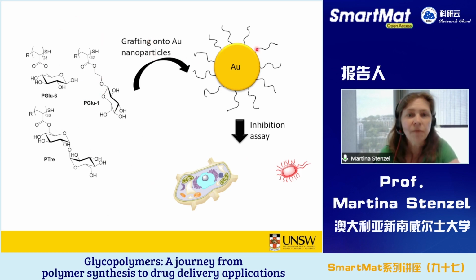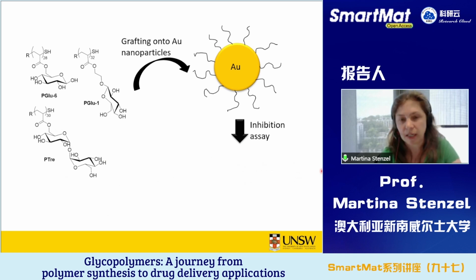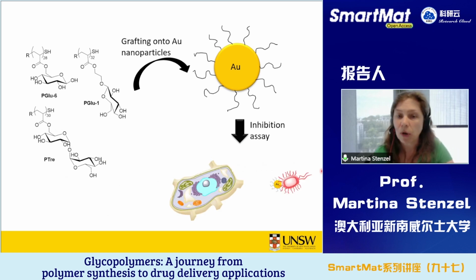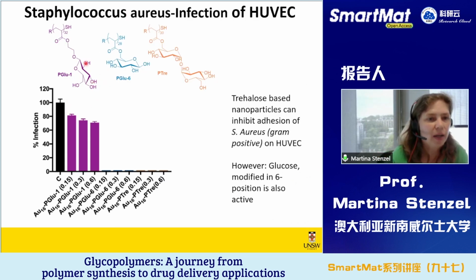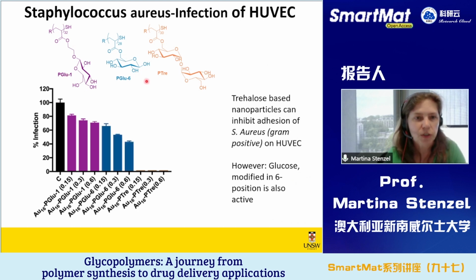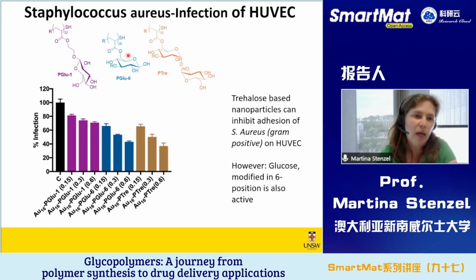Then we took these polymers and we grafted them on gold nanoparticles. The idea is that we have here healthy cells and we have here bacteria, and these bacteria will invade the healthy cells. However, if we now add into our system our gold nanoparticles, these gold nanoparticles will attach to the bacteria, and therefore the bacteria can't invade healthy cells. If we do this, we find glucose alone is already quite efficient in stopping bacteria from invading. However, if we attach glucose to 6th position, or we even use trehalose, we found that these two molecules, and especially trehalose, are very effective in inhibiting the adhesion of golden staph.